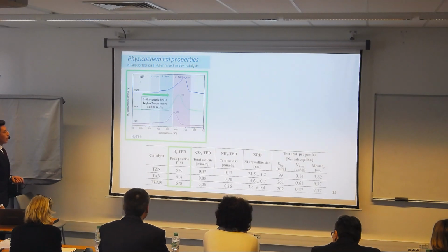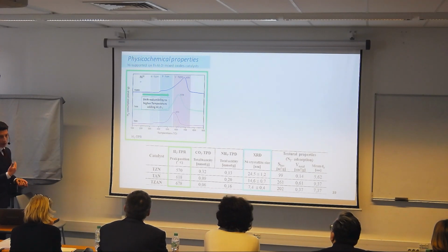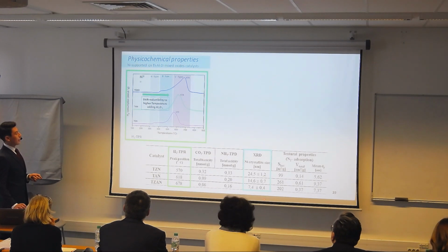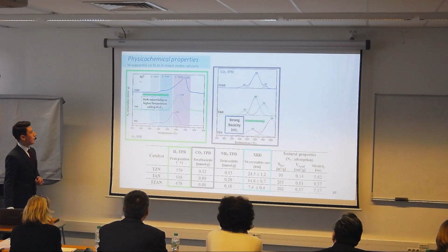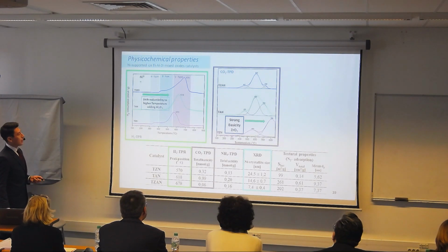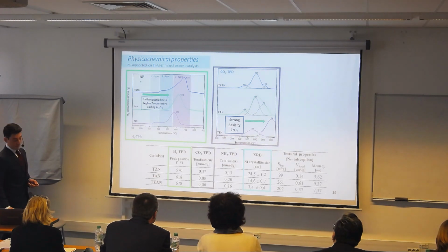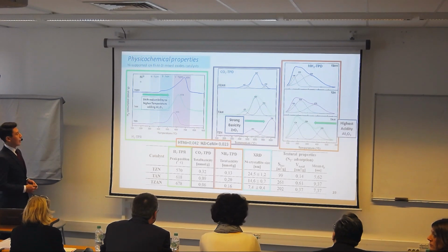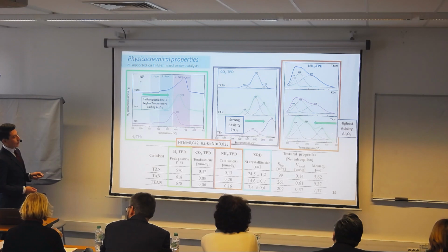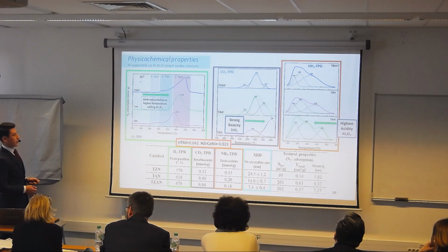We also did the reduction after the test. The reduction by TPR shows that initially the reduction temperature is lower compared to the previous one. For the nickel crystal size we have a variety, but using zirconia produces a higher nickel crystal size. Talking about the basicity, we move to strong basicity when we have zirconia in our oxide. And about the acidity, we have a very high acidity when we introduce alumina in the oxide.